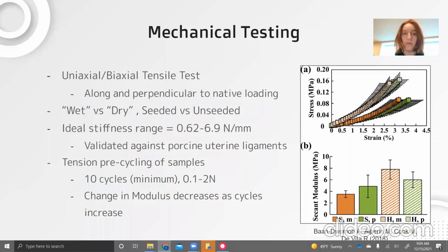Mechanical testing for this implant would be a uniaxial or biaxial tensile test, in which the force would be along and perpendicular to the native loading direction. We would experiment with wet versus dry, in this case meaning encapsulated in hydrogel versus non-encapsulated in hydrogel, and seeded versus unseeded with the cells. The range that we're looking for the stiffness is roughly 0.62 newtons per millimeter to 6.9 newtons per millimeter.